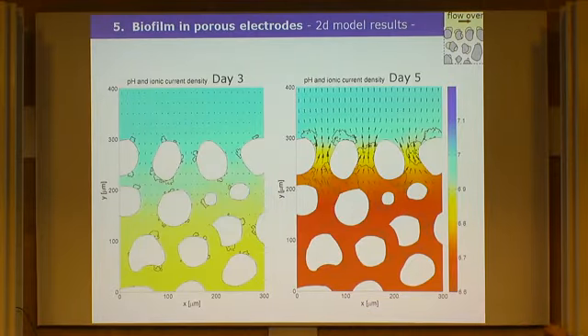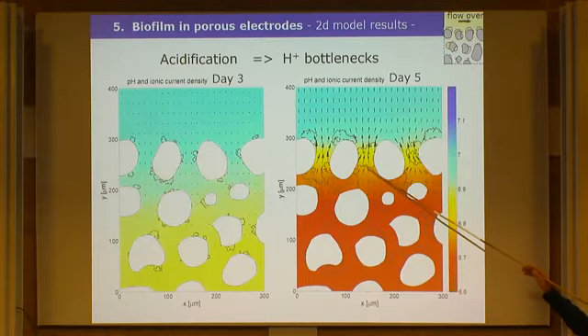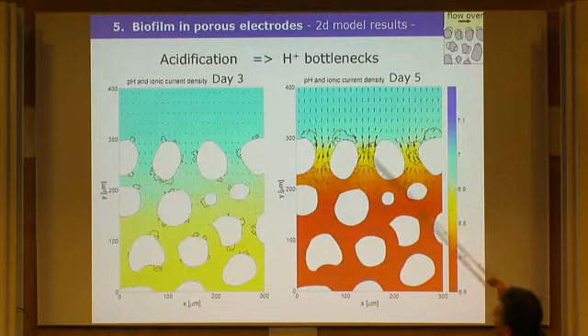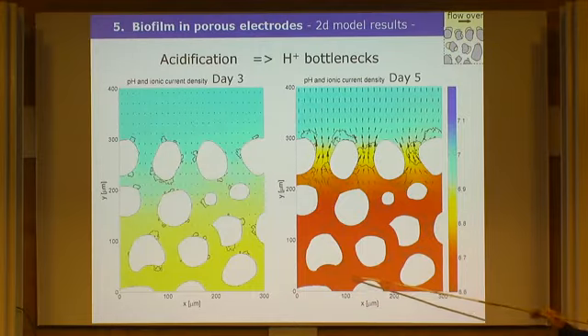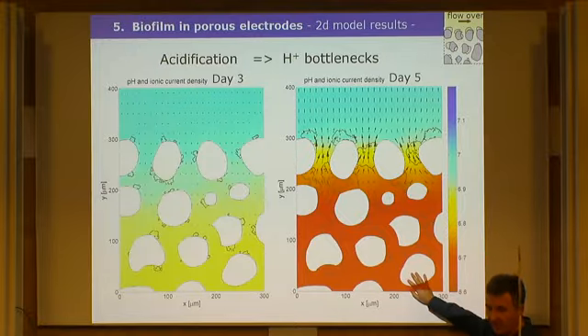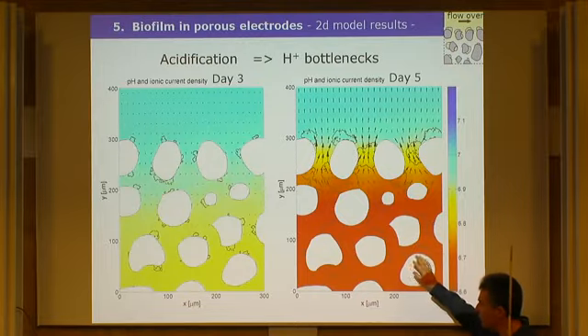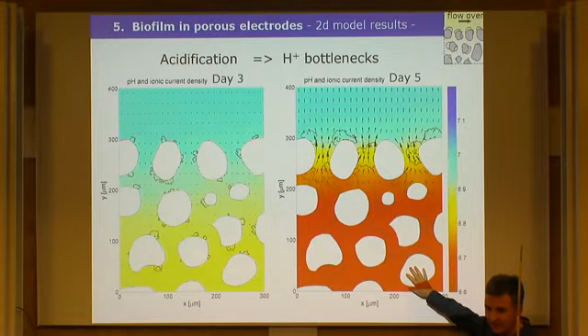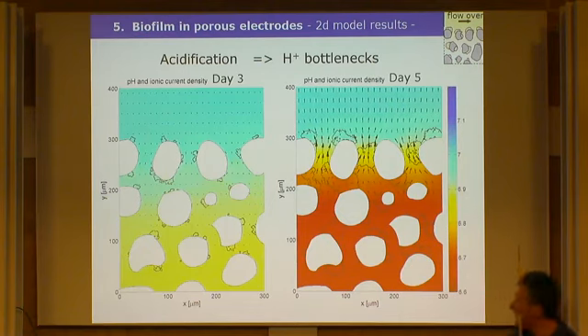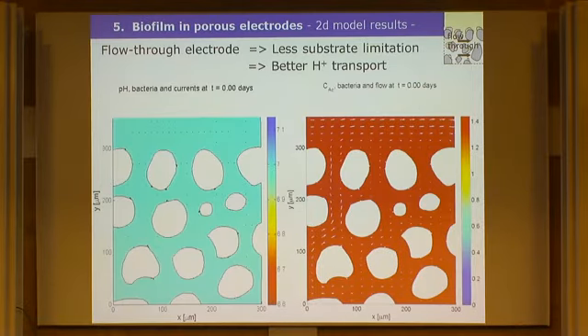And in this graph you can see the protons flowing out, and practically what you see here is an acidification inside the electrode. How do you get rid of this acid here now? This is a problem, because the cells here not only suffer because of lack of acetate, but also because of too low pH. So mass transfer is very important in this case, and many people don't realize this. It should be obvious, but it's not really. So probably with models we can convince them.